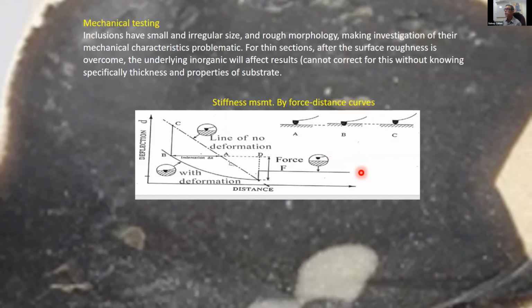Now we want to go to the mechanical information. Anyone who's done some mechanical work with AFM knows that one way to do this is to push a tip into a surface, look at a deformation, and try to correlate the deformation with the force and convert that into an elastic modulus. But when you have a really stiff material, as the things that we're looking at, the difference between this line of no deformation and the bowed one with the deformation becomes very, very small. And you have a huge amount of uncertainty.